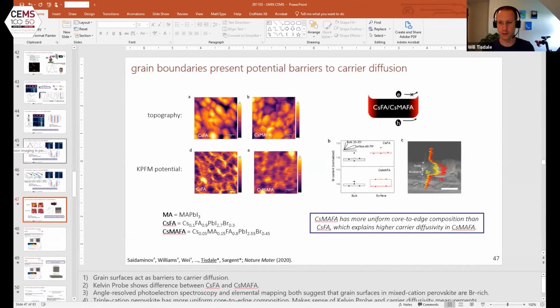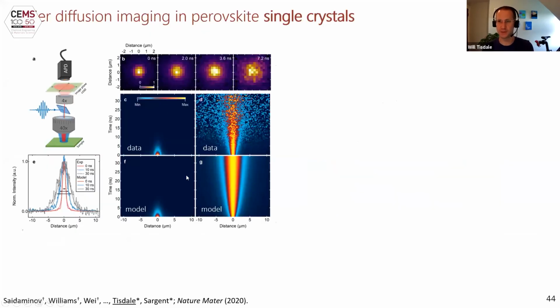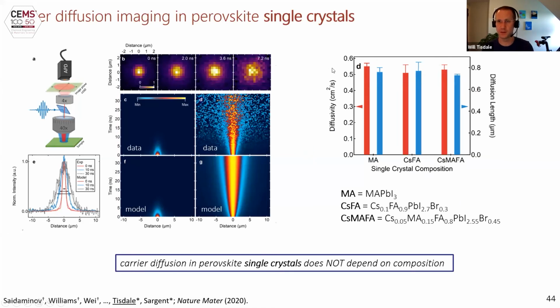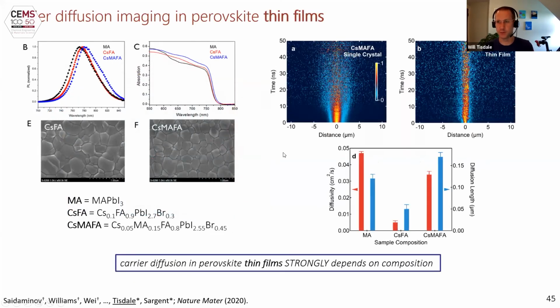So first thing I'll say is we make two observations. We make the observation that in the single crystals, there's no dependence of the carrier diffusivity on the composition. And then we make the observation that in the thin films, the carrier diffusivity does depend on composition. That's as much experimental fact as we have. The rest of it is conjecture and hypothesizing as far as why that is. We also observe that in all cases, the diffusivity for the thin films is lower than it was in the single crystals. And so that suggests that, no matter the composition, the grain boundary is disrupting charge carrier transport. And then the next leap in logic is that, okay, perhaps these grain boundaries are having more or less of an effect on charge carrier transport, depending on the cation composition.